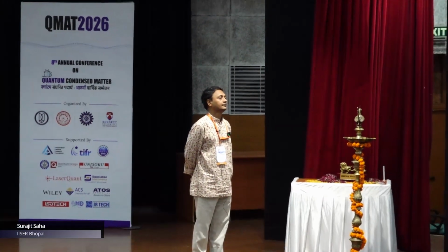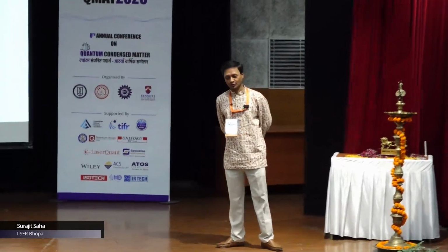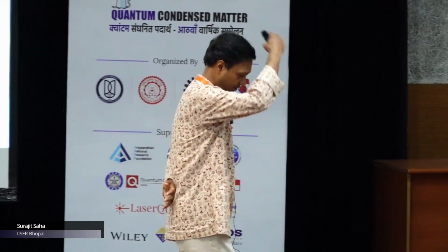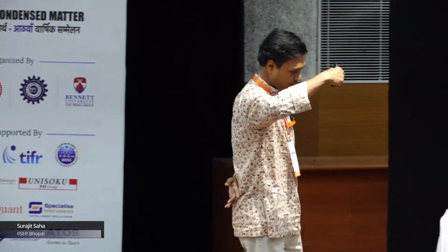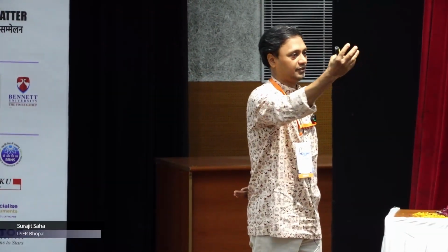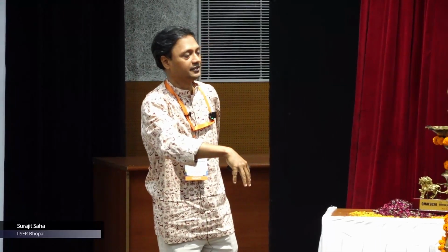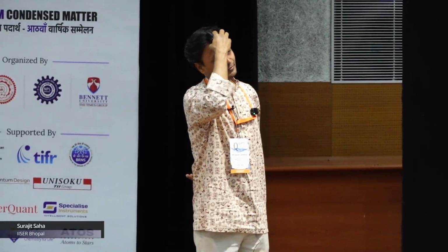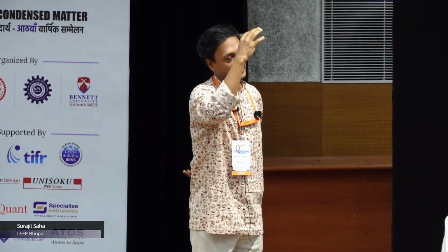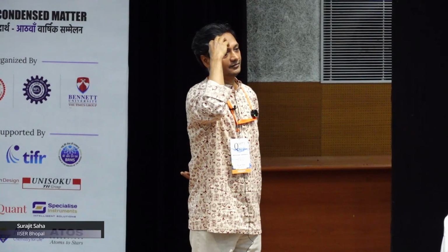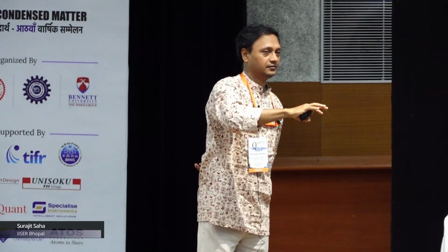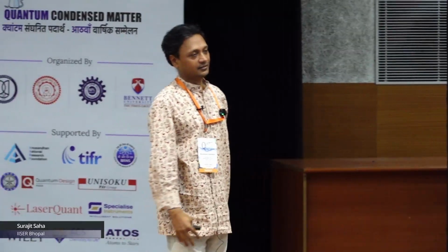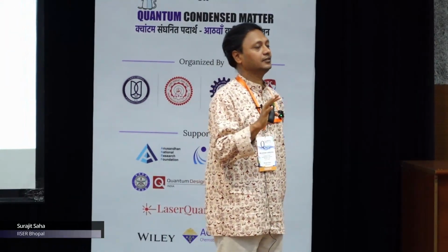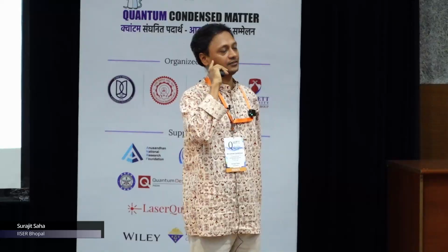What happens if you cool down below room temperature? Okay, we did that. Let me talk about both the phases, especially the alpha 2H to beta 2H. Of course, it has come back to the alpha phase. The other one, the 3R stack, remained in the 3R stack down to 80 Kelvin. We did not go below 80 Kelvin; we would have to try with another cryostat. But down to 80 Kelvin, we could stabilize only the 3R phase.